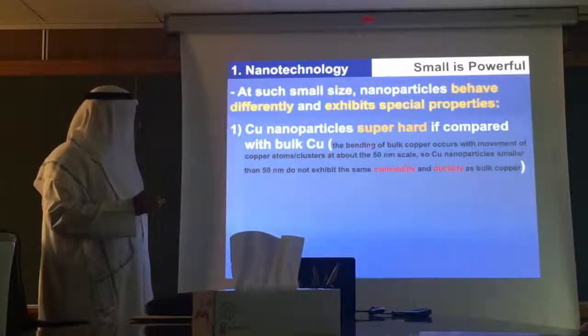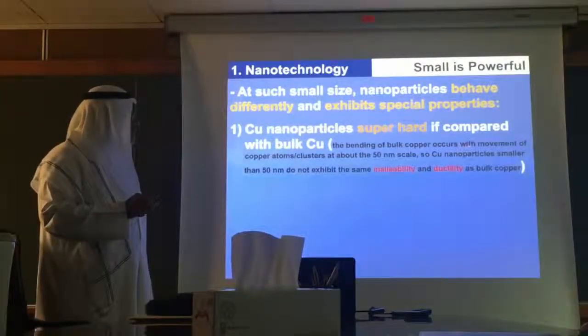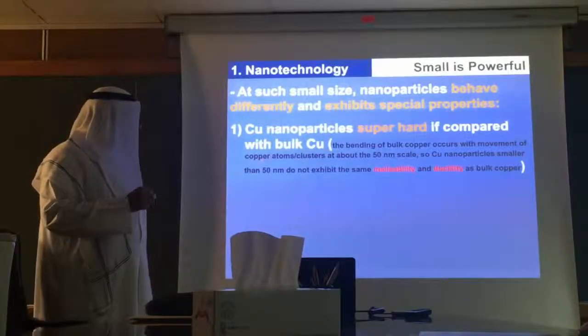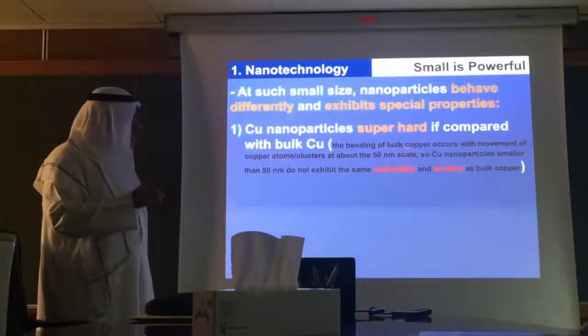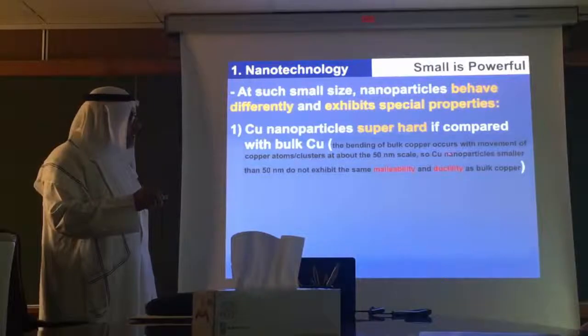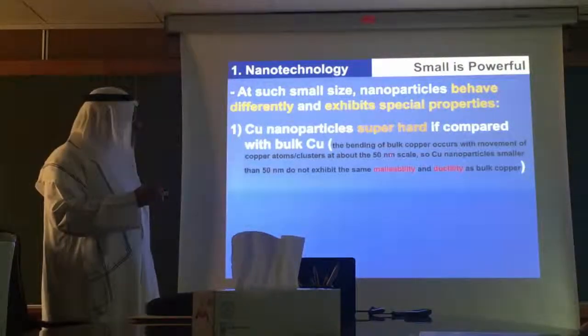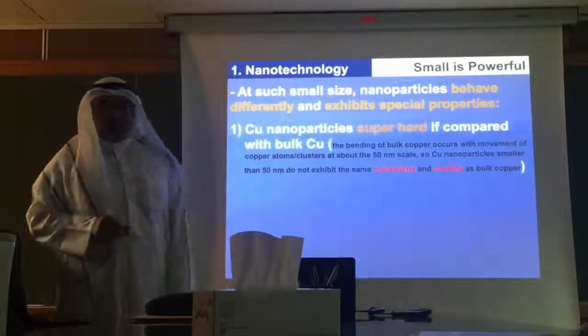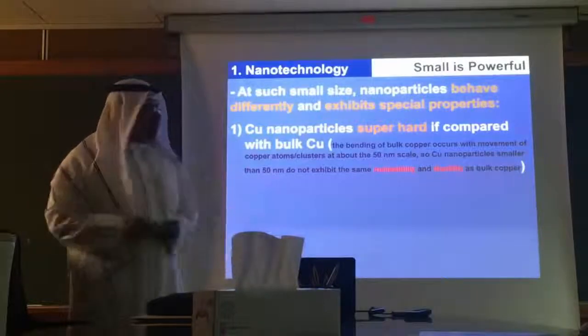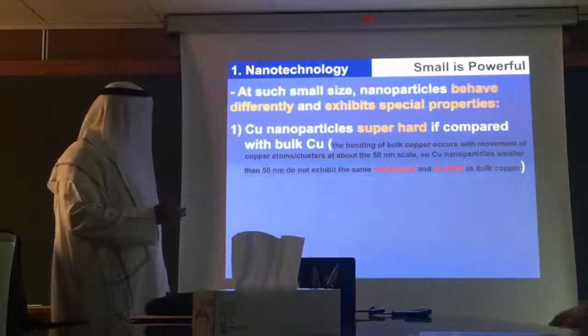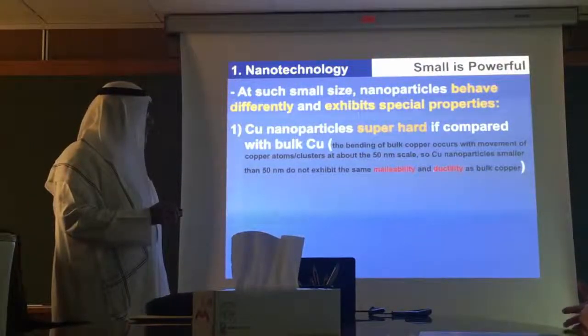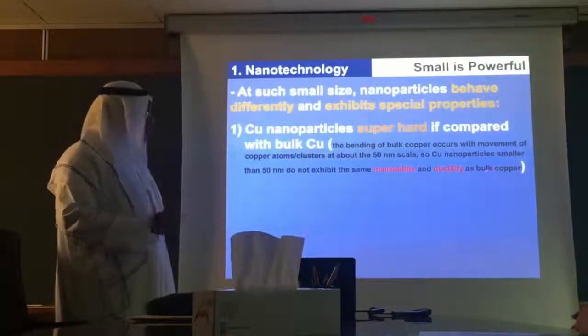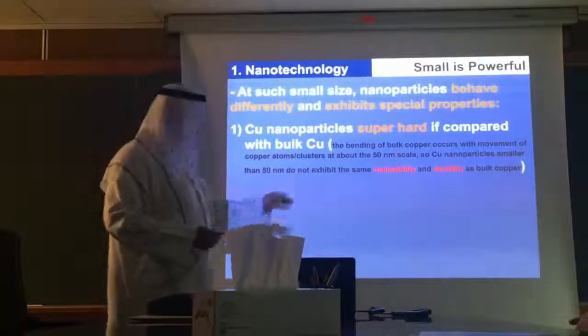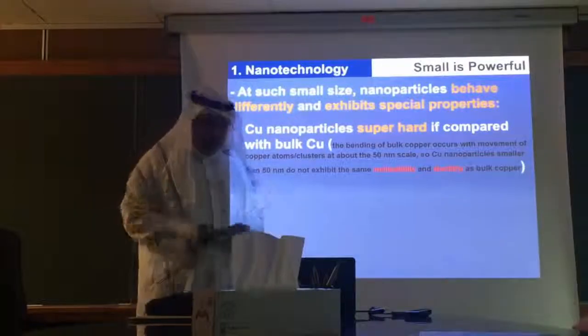The bending of bulk copper occurs with movement of copper atoms in a range scale of 50 nanometers. So if I make my copper less than 50 nanometers, this movement will be lost. The malleability and ductility of the material will not be as good as for the bulk. So we are talking here about changing some mechanical properties by decreasing the size.